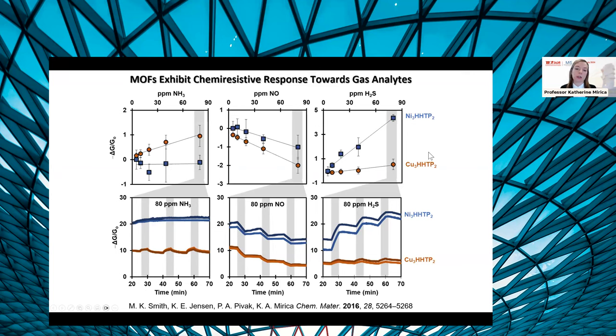So I want to draw your attention to several important features emerging from this data. First, we see a concentration-dependent response upon exposure to these gases. From this concentration-dependent response, we can derive limits of detection for these sensing devices, which are in the low part per million range for nitric oxide and hydrogen sulfide. Second, we see different responses of different materials to various gases. So let's take a look at nickel hexahydroxytriphenylene versus copper hexahydroxytriphenylene as they respond to ammonia. We see a reversible response for the copper-based material towards ammonia, but essentially no response of the nickel-based material towards ammonia. So there's some selective response, and that can be useful for differentiation of gases.